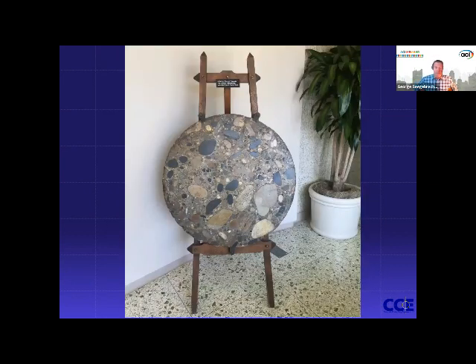If you've ever gone to PCA's headquarters in Skokie, in the lobby is a core from the Hoover Dam. It's something I can't walk by almost any time, and I've seen it 1,000 times without staring at it for a while and thinking, okay, that's the greatest generation that built it. It's just amazing what they did in those days. They used, I heard, 600 miles of cooling pipe, 1-inch diameter cooling pipes going through the entire construction to cool down the heat of hydration to avoid these detrimentally high temperatures of heat of hydration. And they placed those in 4x8 cubic yard buckets.